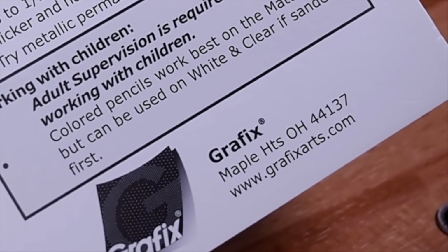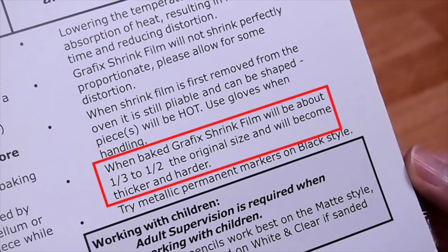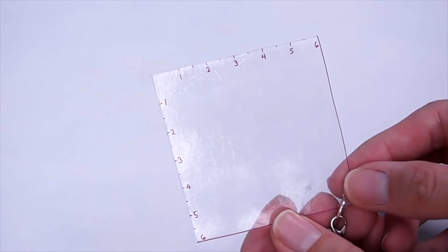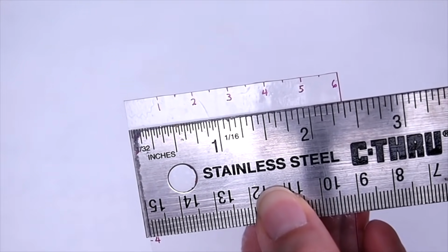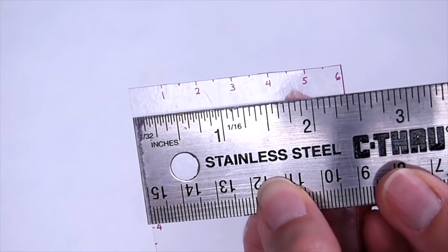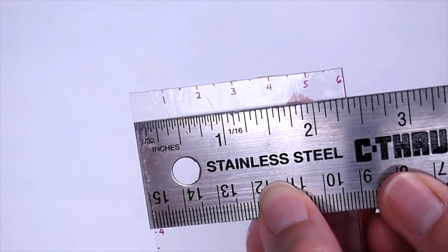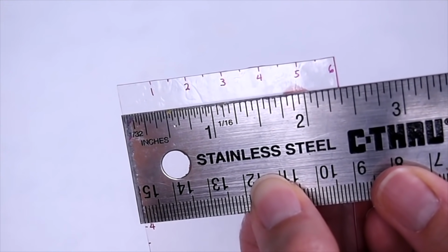So the amount of shrinkage will depend on the brand. The one I'm using shrinks to about a third to half its original size, but some brands can shrink smaller. To get a rough idea of how big your original artwork should be, I recommend making a ruler like this out of the shrink plastic you are using. This way, you'll have a general idea of how much your artwork will shrink. As you can see from my ruler, mine shrinks a little more than half of the original size. So based on that, in order to make a decent sized charm, I make my artwork around 3 to 4